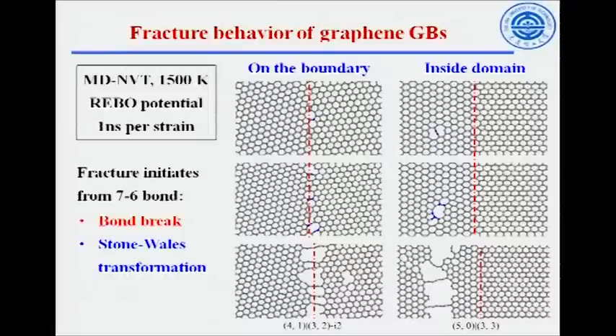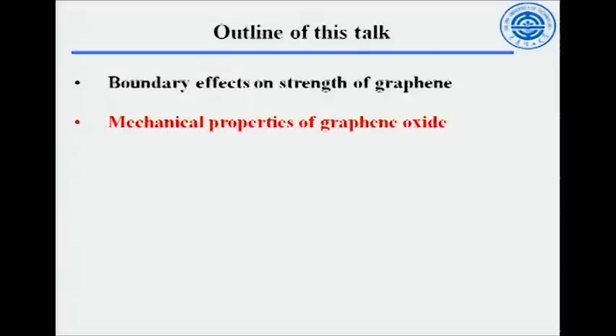The intrinsic strength also changes with formation energy, ranging between 70 and 100. So basically, we have some systematic trend which might be useful to guide future experiments. We further examine how this system fractures under sufficiently large tensile strain. We run MD simulation, not ab initio, but empirical MD simulation. Interestingly, we find that the initial fracture may happen either on the boundary or inside the domain, which is indeed unexpected. The fracture initiates from either breaking of the bonds or a Stone-Wales transformation. So this is the first part of my talk.